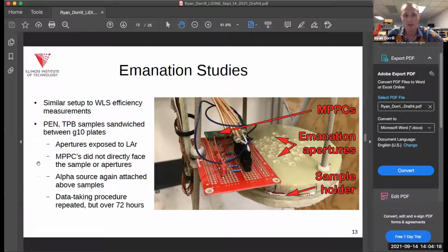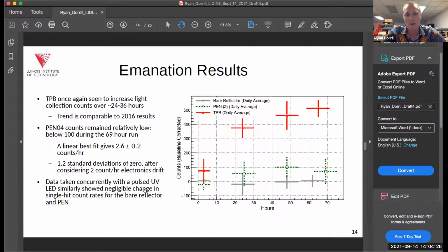So we then took the data like we did before, however, over a period of 72 hours, a longer period of time than those initial measurements, which were 6 to 8 hours. Here are the results. What you see is the red crosses that are sharply rising at the top are the TPB samples. So once again, we saw these rising count rates for the TPB, whereas the PEN was consistent to within about 1 sigma with no rise, although there is potentially a slight rise here.